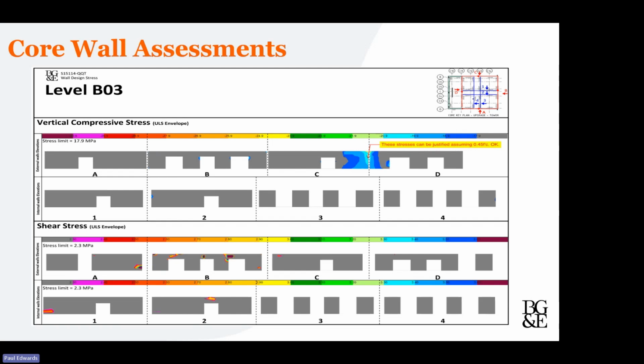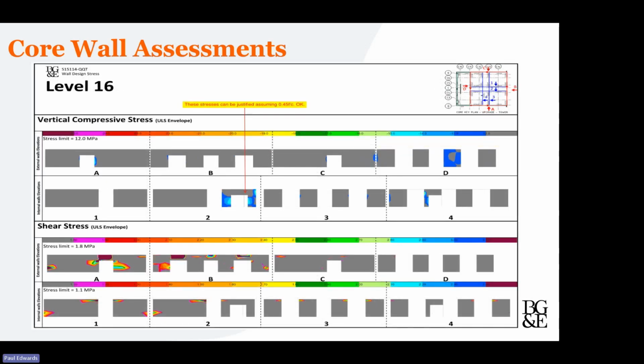And with this information, you can start to see the plots for compressive stress and shear stress on the core walls, expressed as an unfolded envelope. Comparing this to the Schmidt-Hammer testing and the destructive testing helped to understand where weak concrete combined with areas of overstress. And as we work our way up the building, so that first slide was level 3. This, for example, is level 16, where there start to be some areas where stresses are increasing, and the actual applied design stress in the building you can start to note in the top left.